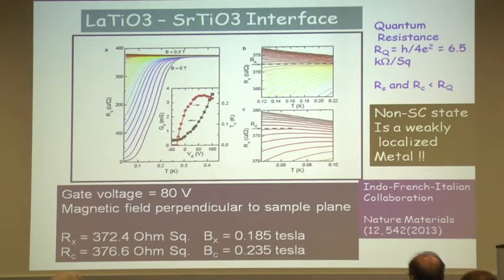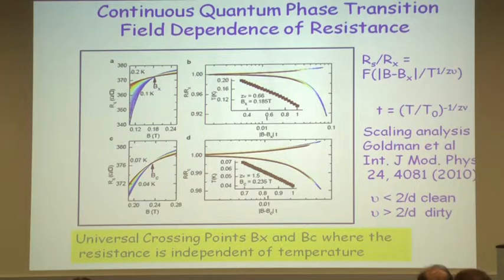Now, if I just keep blowing up this portion a little more and go to still lower temperatures, from somewhere 0.06 to about 100 millikelvin, I find another region here where the resistance is independent of temperature. It defines another critical resistance RC and a corresponding critical field BC. And these are signatures of a continuous quantum phase transition in the system from a superconductor to a weakly localized metal. One can do a detailed analysis of this quantum phase transition.